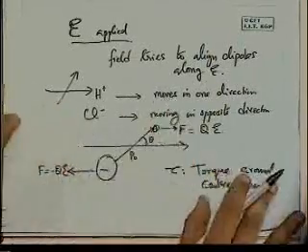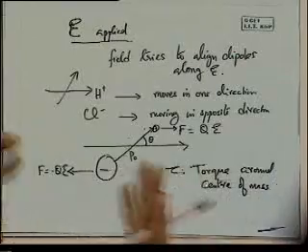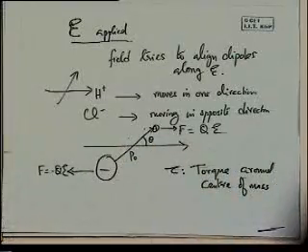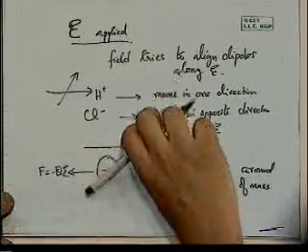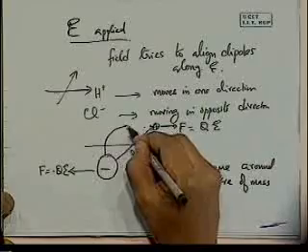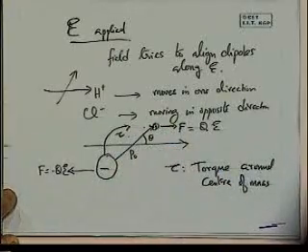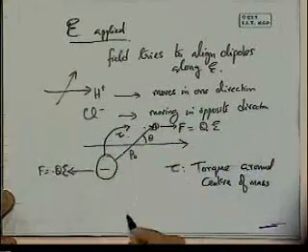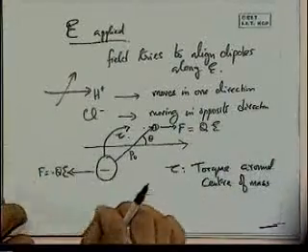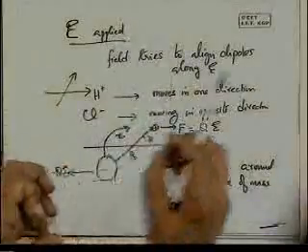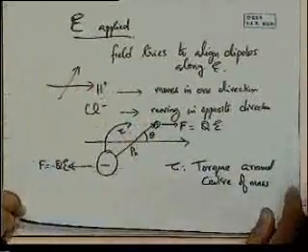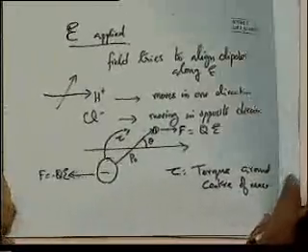So instead of them just freely moving off and aligning themselves with the field, because they are bonded together as part of the hydrogen chloride molecule, or whatever we are considering, the particular example was HCl, it will seek to rotate, and there will be a torque tau experienced by this molecule. We are neglecting something here, that the effect of this field will also be to slightly stretch the bond. Okay, this and this will slightly get stretched, but that's a smaller effect compared with the torque trying to orient it around the center of mass.